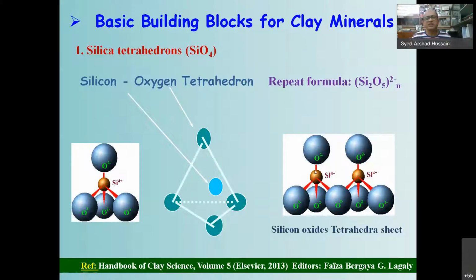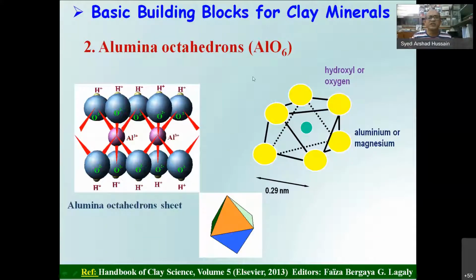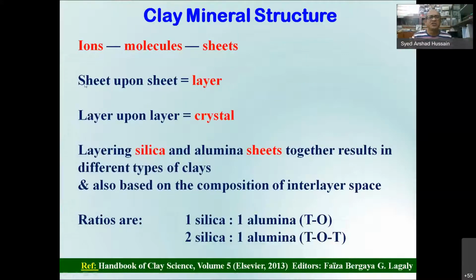This is just a simple idea of the silica tetrahedron, this one, and they form a sheet like this. And this is the alumina octahedron, this one unit, and the repeat unit forms the sheet. Sheet upon sheet forms a layer, layer upon layer forms crystals, and layering of these silica and alumina sheets forms different types of clay. Also, of course, the composition in between the layers makes different types of clay. Mainly 1 silica to 1 alumina, we say it's TO type clay. 2 silica, 1 alumina, we say it's TOT type clay.